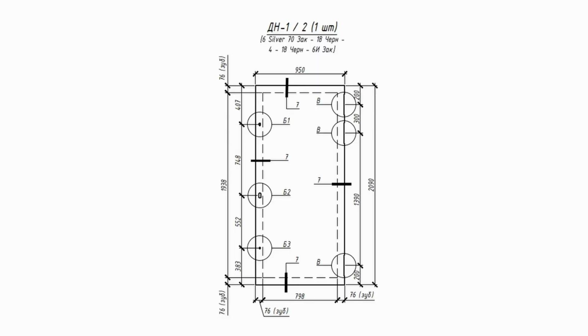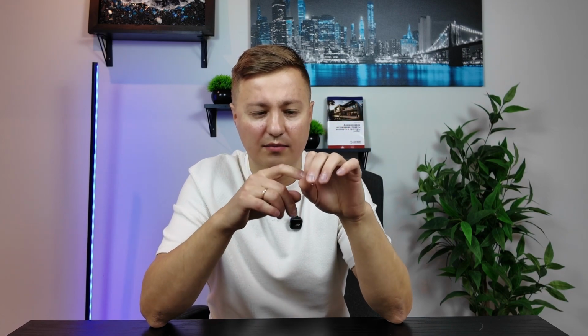Of course, in this structural glass, you need to provide holes for the handle, for the lock, for the cylinder, and so on. As for installing various handles in this kind of structural glass, first of all, make the holes for the handle larger in diameter, because I had problems when I made them really tight. The handle was pulled, it played a little, hit the edge of this hole, the glass unit burst. So make the hole larger in diameter. Be sure to bevel the edge of the hole. Include all of this in your order form. Blunting, beveling, basically make sure the edge is finished as much as possible so there are no microchips.